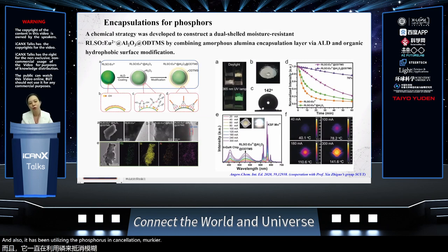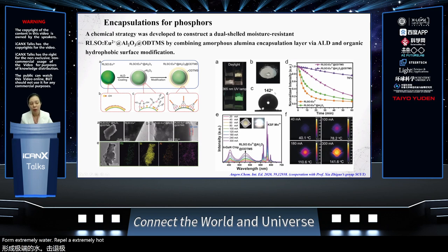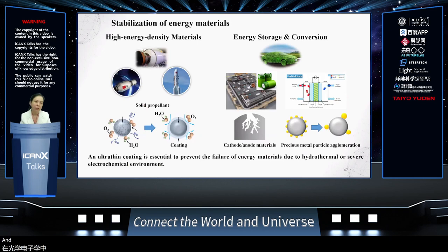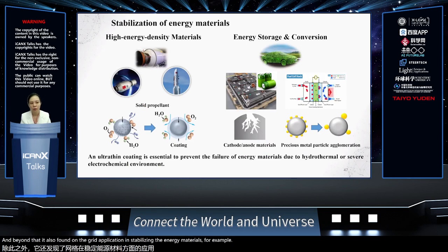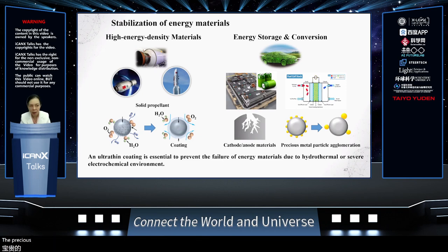Like here, we run two steps of self-assembled structures with the ALD processes. And it's actually helping to form extremely water-repellent, extremely hydrophobic coatings to make sure that these normally very easy-to-wet powders are able to survive in the application. So the encapsulation by ALD definitely found a lot of applications in optoelectronics. And beyond that, it also found great applications in stabilizing energy materials, for example, solid propellants, lithium ion cathodes, precious metal particle agglomeration, etc.